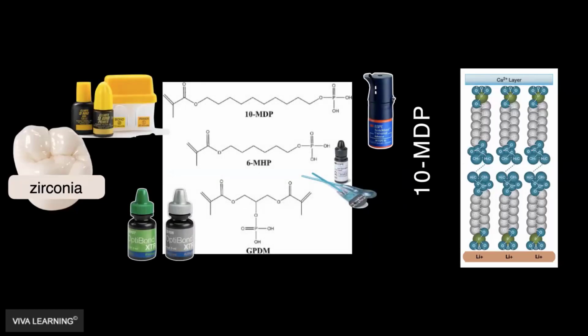Now, there are a number of different monomers in the different adhesives that are out there. So Clearfil SE, right? Kuraray was the first one who came out with MDP long, long ago in Clearfil SE, right? That was the first really breakthrough, and it's been super successful. Once the patent ran out, then 10-MDP got put into tons of different primers, right? Scotchbond Universal, obviously heavily researched. They put MDP in there. What's interesting is that 3M also has another one, Prompt L-Pop, that 7th generation bonding agent, that has MHP in it. It's not even MDP. So that is not nearly as good as the 10-MDP.